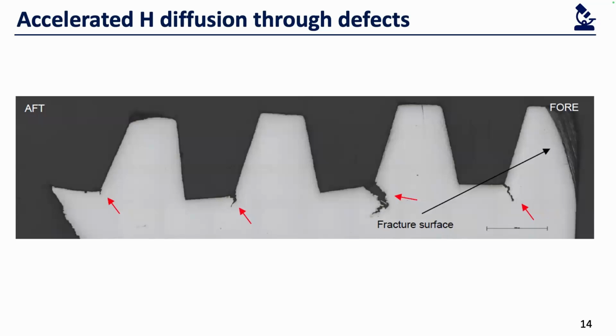And also, as you can see here, where we see the cracks, this is taken from the failed component. Those cracks always happened at the thread roots, where the stress concentrations are located. And there, in these areas, we believe that the local behavior of the microstructure shouldn't only go through yielding, maybe it's also beyond the yielding and reaches plastic deformation. That's why we already have some breakage of the microstructure features, or we have already induced some vacancies, and those failures can promote the hydrogen diffusion, and so they assist the cracking at these stress concentration areas.